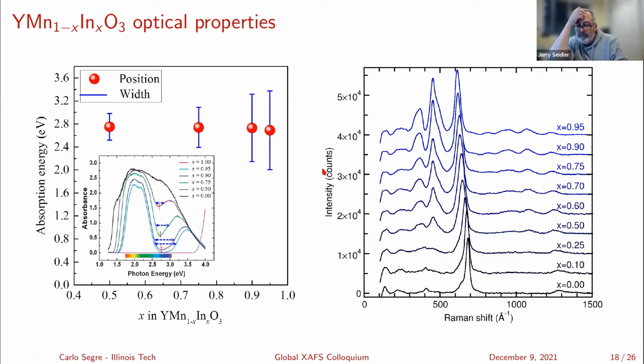I guess my first question for you is, you're taking a model of superposition of two phases, two endpoint phases, and do the fit coefficients you get for the linear superposition at the XANES agree with the fraction that you infer for the two-phase mixture from the EXAFS? Yes, they do. They're basically identical. We just didn't plot them on that figure, but they're identical. Okay. We just wanted to confirm it with the EXAFS as well.